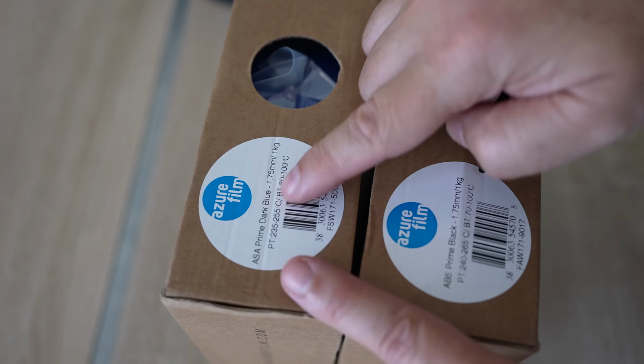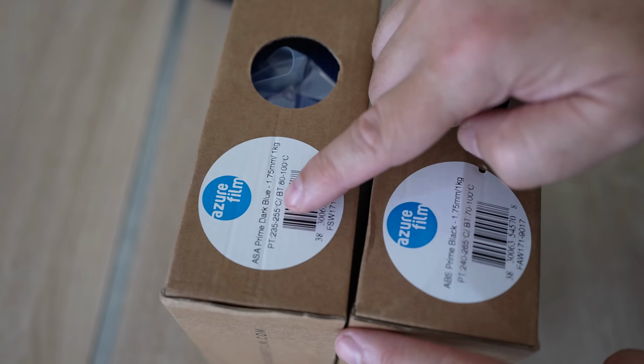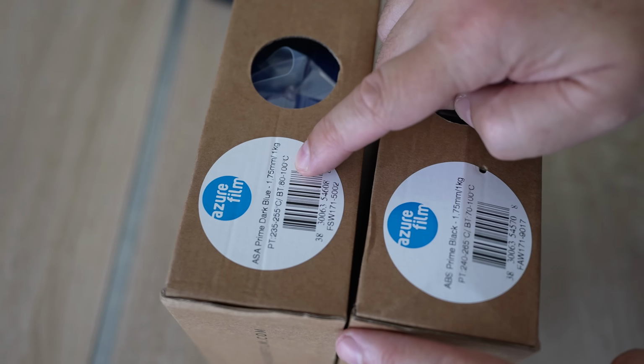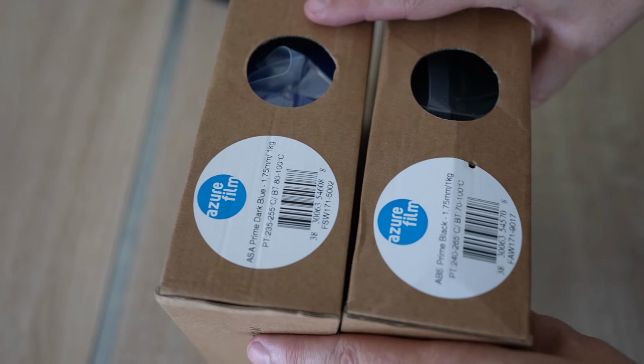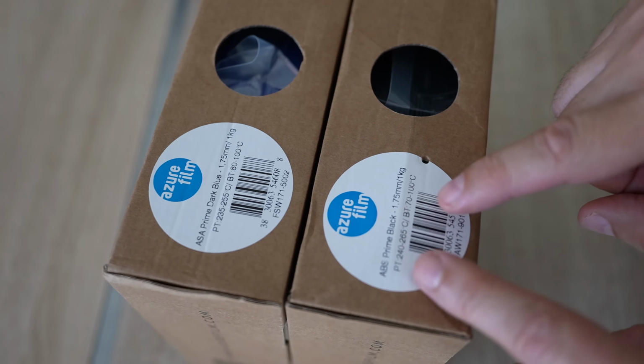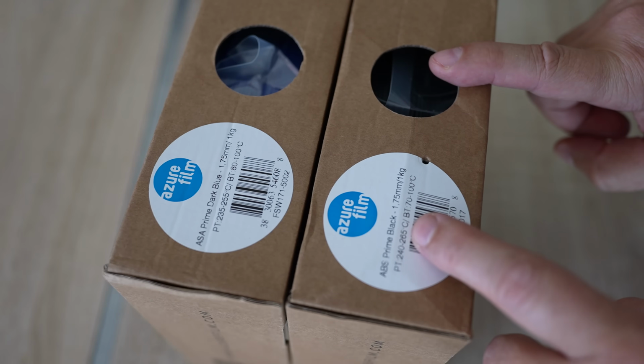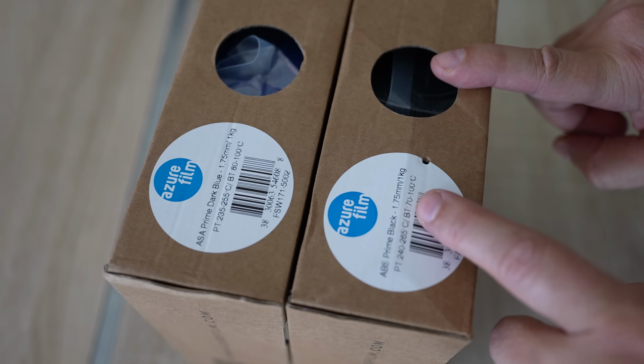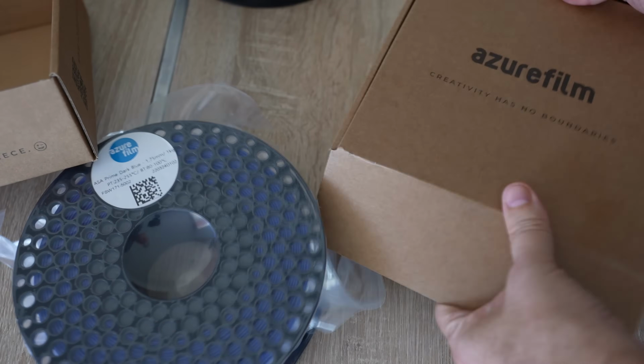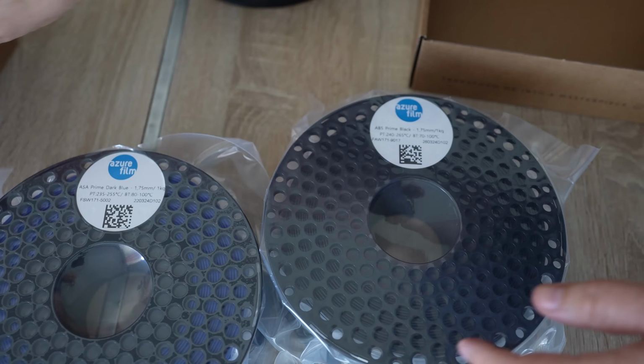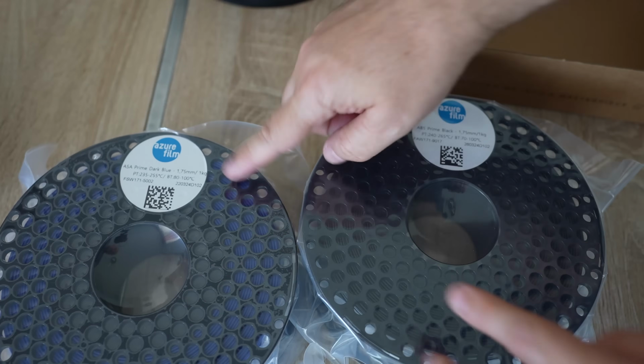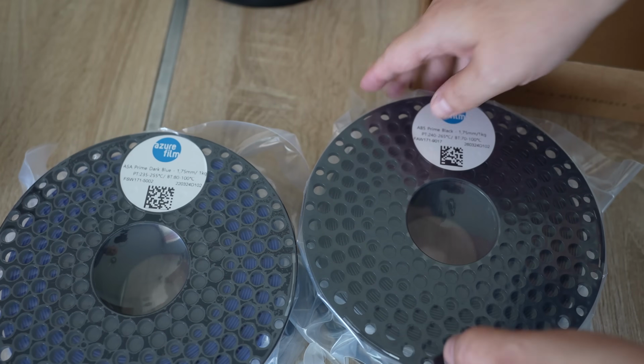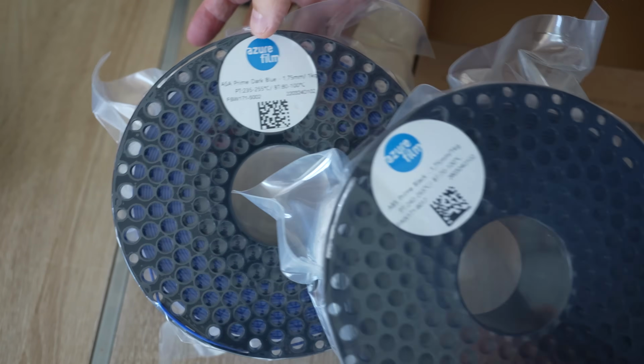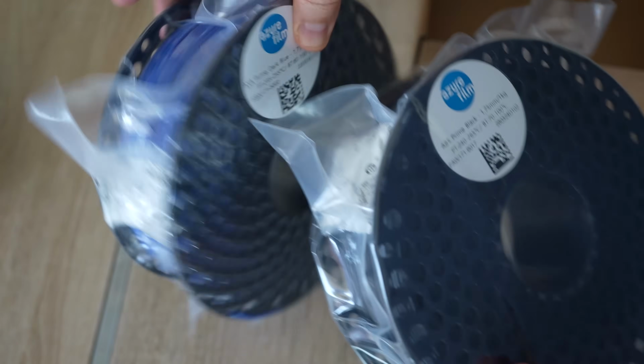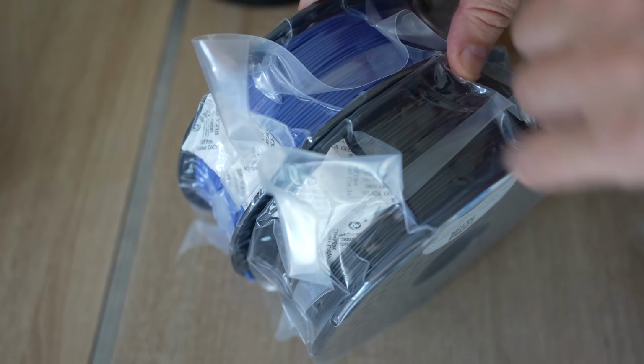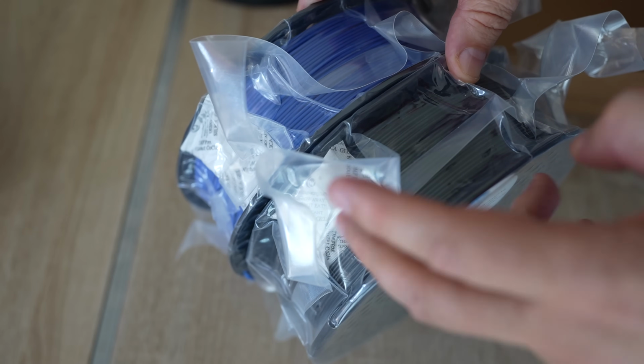ASA Prime is in dark blue color, the print temperature between 235 and 255 degrees Celsius, and bed temperature between 80 and 100 degrees Celsius. The ABS Prime is in black color, and the print temperature between 240 and 265 degrees Celsius, bed temperature between 70 and 100 degrees Celsius. They have these spools with a lot of holes, so we can easily lock the end of the filament. And the same information we have on the sticker, like on the box. And both have this nice vacuum packaging with some desiccant inside, and I will open them before the printing, but without drying.